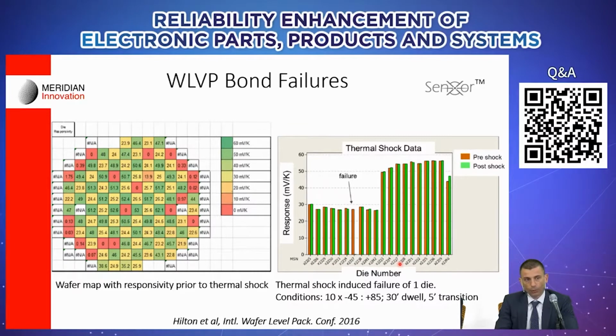So here I show from literature a typical wafer map of a thermal imaging sensor. In this case, this is a microbolometer, which has been subjected to thermal shock type of stress, where the wafer is inserted after bonding. The wafer is subjected to very low temperature, -45 for some 30 minutes, and then suddenly moved to a very high temperature of +85 within a 5-minute transition. My understanding is that this happens with dual chamber machines that can support 2 different temperatures and have an automated way of changing the devices under test from one chamber to another.